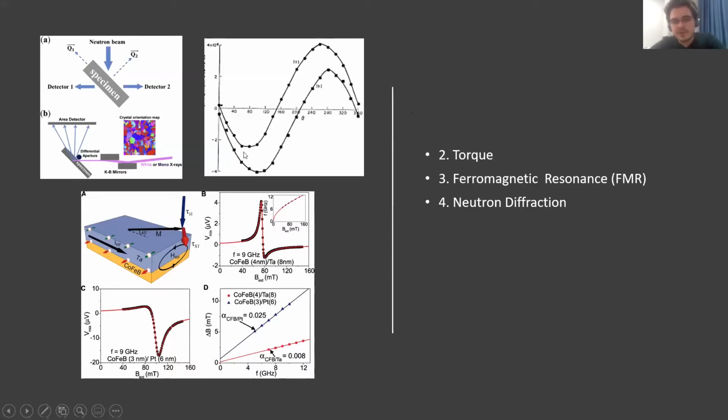This rotational hysteresis also exists in single ferromagnetic layers. But in single ferromagnetic materials, this hysteresis loop only exists in the small applied field regions. But as Meiklejohn and Bean observed, this rotational hysteresis is a non-vanishing characteristic of exchange bias. We can have rotational hysteresis even in large applied fields in our ferromagnetic and antiferromagnetic bilayer system.